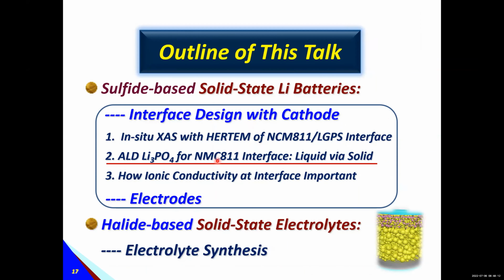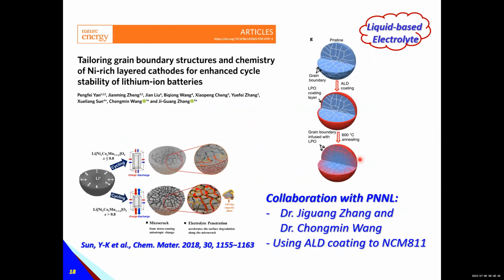So next example, we try to use ALD to synthesize lithium phosphate as a coating on this interface, particularly comparing the liquid system and the solid, what difference. So we have one study, a collaboration with PNNL, with Dr. Jiguang Zhang's group and Dr. Chongmin Wang's group. In that work, we try to understand NMC 811. We have cracks along the grain boundary. So we try to address this challenge by having a coating, ALD coating first.